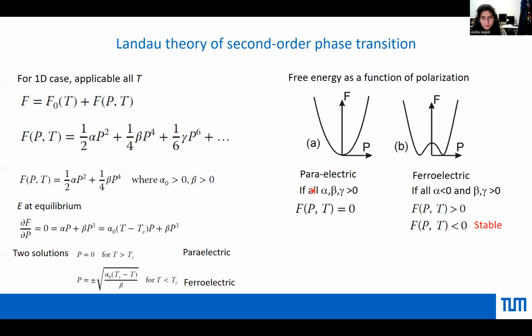With this expansion, how do we usually find the suitable situation in equilibrium? The free energy you want to have at minimum, so the derivative of the free energy you will equate to 0. If you take the derivative of this equation, you will get this, and if you put it equal to 0, you have two situations. One where polarization is 0, which is the paraelectric situation, and the other one where polarization is either positive or negative, two minima, as a function of T, and here T is smaller than TC. In some further lectures, we can also actually plot it and see how it looks.